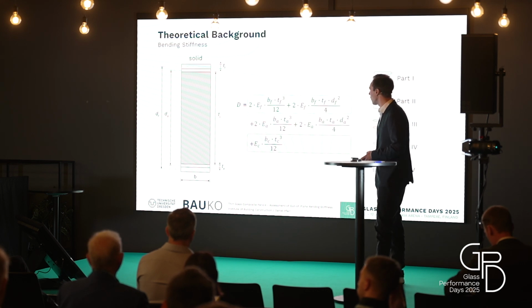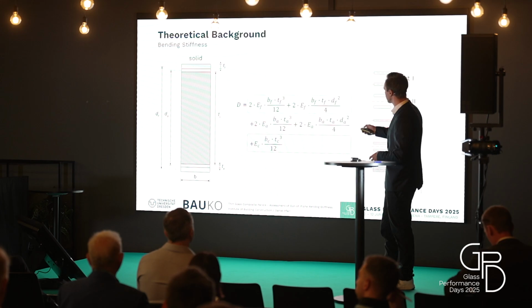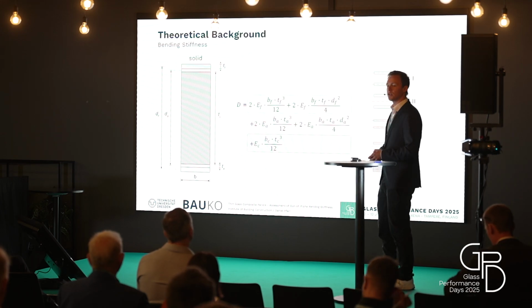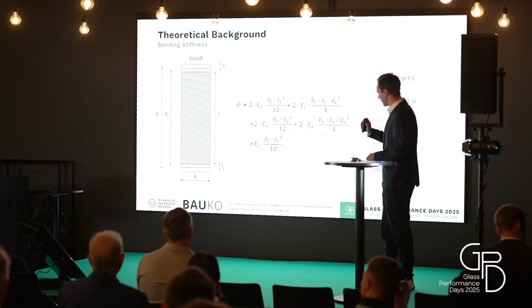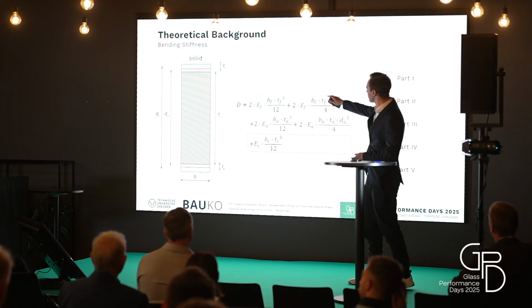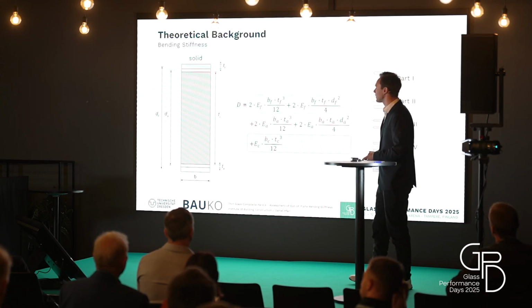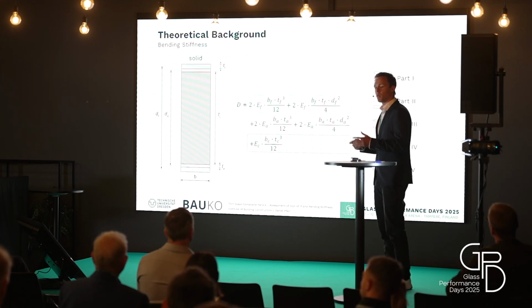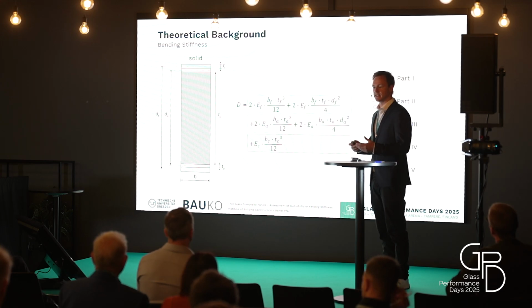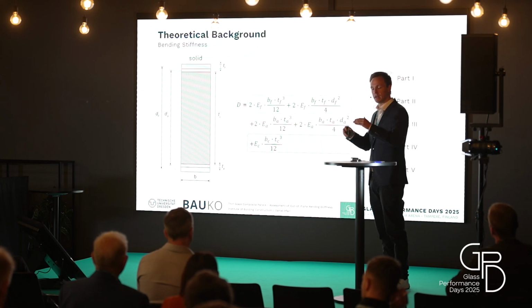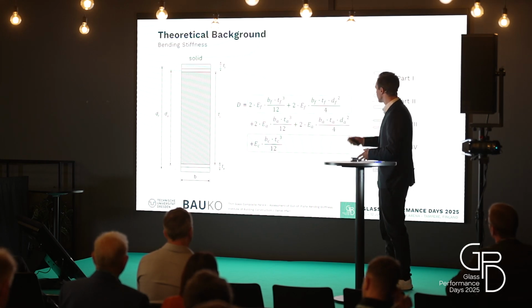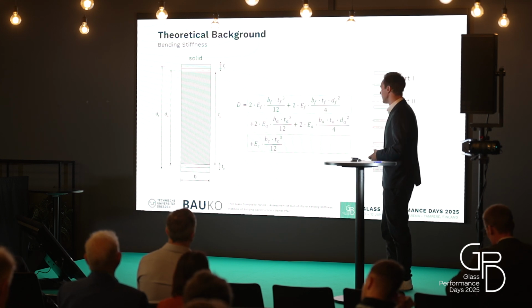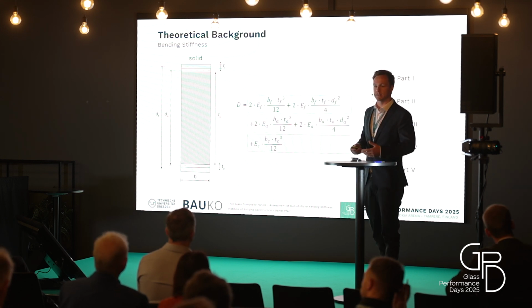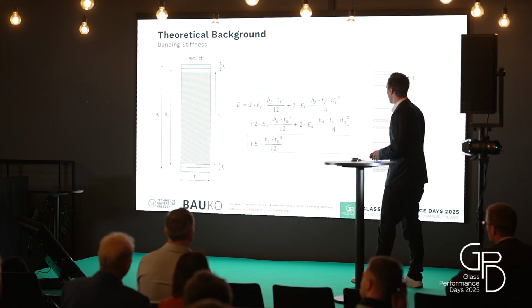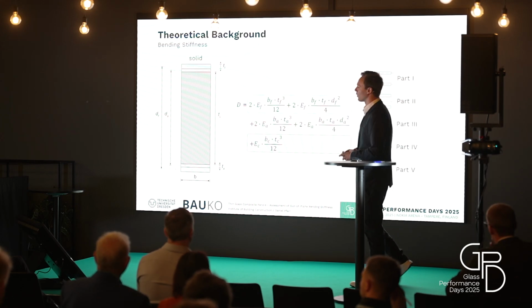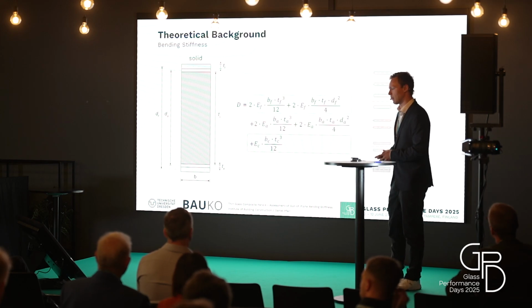So we have a formula for the calculation that consists, like the composite, of 3 different components. The upper one, I think it is highlighted in blue, is accounting for the thin glass, and we have 2 parts here. One is accounting for the bending stiffness of the glass around its own center, or around its own neutral axis, and the second part, here marked as part 2, is the bending stiffness of the glass around the neutral axis of the whole composite, which is a major part because we have the distance of the whole core and adhesive adding up and distancing our glass from each other.